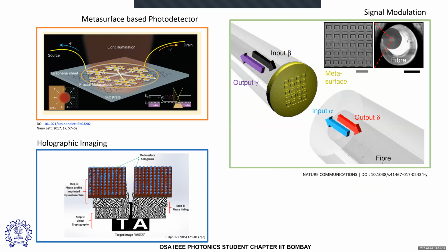In the first case, the meta surface patterning, which is a snowflake-like structure, couples with the graphene layer and introduces a strong plasmonic coupling, which increases the absorption response of the graphene. Secondly, we have the signal modulation, where you can have a meta surface patterning which can control the propagation of light in either direction. So in this optical fiber, you can have NOR gate and AND gate functionalities by absorption, reflection, or full transmission of the light in either of the directions. And then we have holographic imaging, where you pattern different antennas on a flake, where all those antenna dimensions introduce a phase, and those phases constructively or destructively interfere to give rise to an imaging pattern.